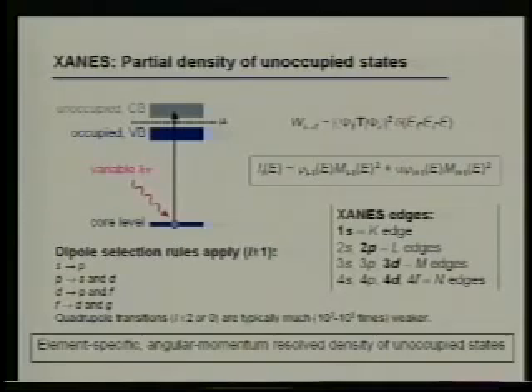So here you can see that the technique is, number 1, element specific, because you're starting with a core hole, and the core hole is localized to that atom. And number 2, these are angular momentum resolved densities of states, because there's a selection rule associated with the transition.